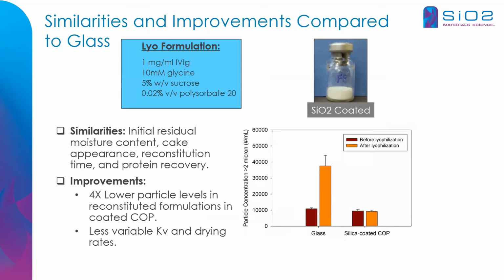We did a practical case study with an IVIG drug formulation, and we repeated this lyophilization study measuring particles greater than 2 micron. And again, here it's a side-by-side comparison of the SiO2 vial and the glass vial. And you can see much lower subvisible particles. Also, looking at the lyo cakes, they looked very similar and also had a similar moisture content and appearance, but as far as subvisible particles after reconstitution, much lower in the SiO2 container.